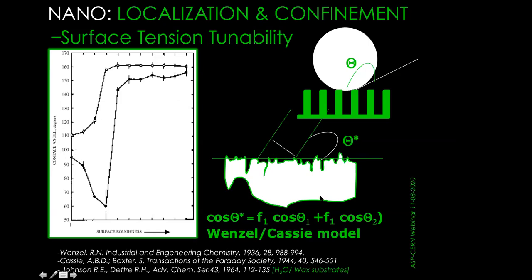What does it mean? At that time, they were not capable of designing nanorods as we are capable of doing now. That was just after the First World War, and before and after the Second World War. So what does it mean? That means, as this graph tells us, or this model of Wenzel-Cassie tells us, if you have a rough surface whereby you can control the roughness of this surface here, you will be able to control the contact angle. And if you control this contact angle, theta, you will be able to control the surface tension, because the surface tension is related to this angle here. So that is exactly what we do with the field of nanosciences and nanotechnology.